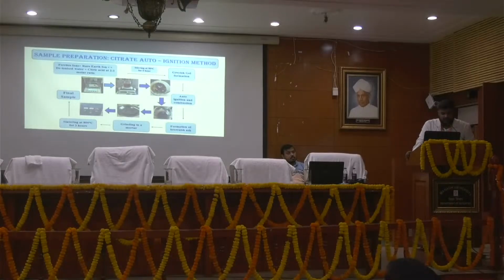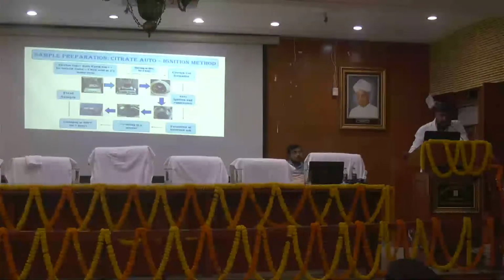This is a flow chart in which I have tried to show how I have prepared the sample. First of all, I have measured all the samples with accurate weighing on the weighing machine, and then we have stirred the sample for 6 hours at 80 degrees, and after 6 hours we will notice that there is a grayish gel formation in the sample, and then after some time it undergoes auto combustion, just like its name, it auto combusts, and then it goes to powder form, and after that we will grind the sample in the mortar, and after that we will perform sintering at 800 degrees for 3 hours, and then we will get the final sample, and we will make it into pellets and measure the different parameters.